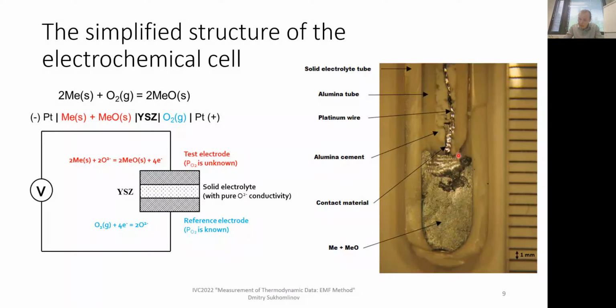So this is the test electrode compartment. Then we have this ceramic tube with closed end. And then we need another platinum lead wire outside in contact with the solid electrolyte. And then we are basically flushing the outer surface of the electrolyte tube with our reference electrode gas. So oxygen, air, it can be something else. And the cell should be rather small, because if it is small, then we keep temperature gradients over the cell at minimum, practically less than 1 degree, through isothermal conditions.